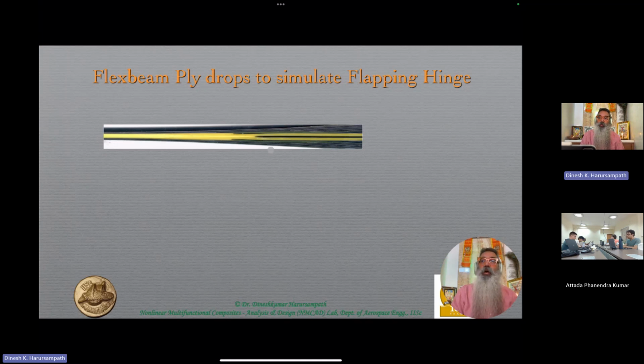And where the plies get dropped, you typically will have a matrix-rich region as well. The reason you have that matrix-rich region is to ensure that the stress transfer takes place smoothly. If you remember, I showcased a situation where you had an unwanted breakage in a fiber in between, and we saw that when there is no matrix, that fiber becomes useless. But in the presence of the matrix, there's an appropriate stress transfer within just a few microns, which is the order of magnitude of the diameter of the fiber in this case, and therefore it becomes quite effective.